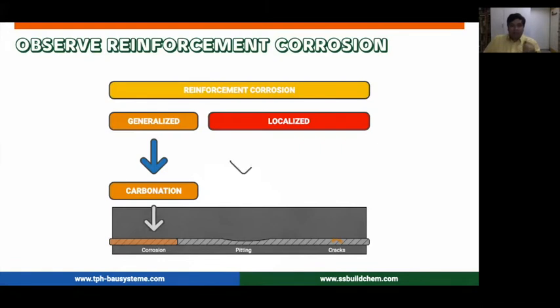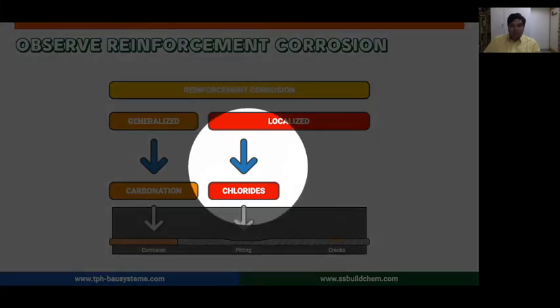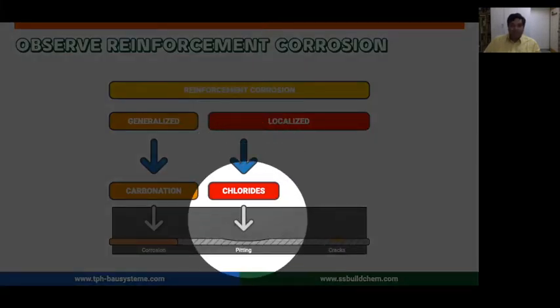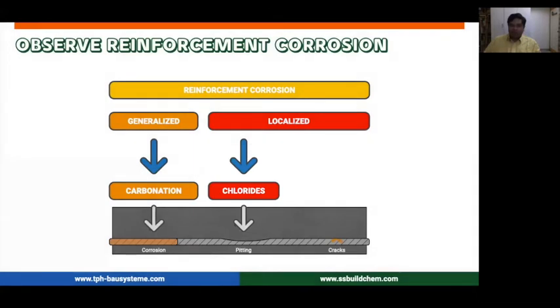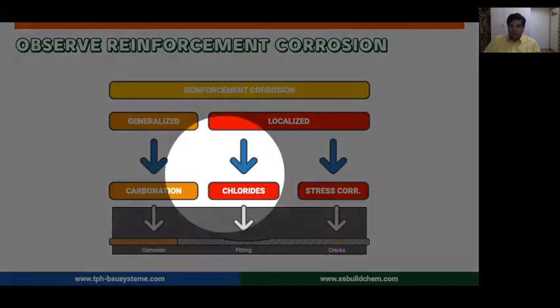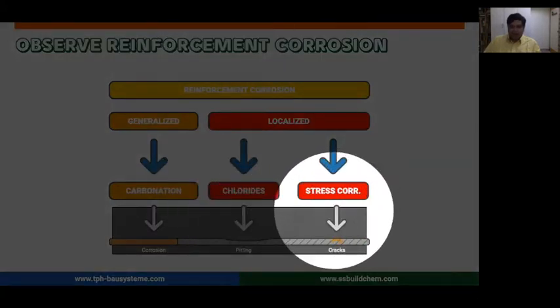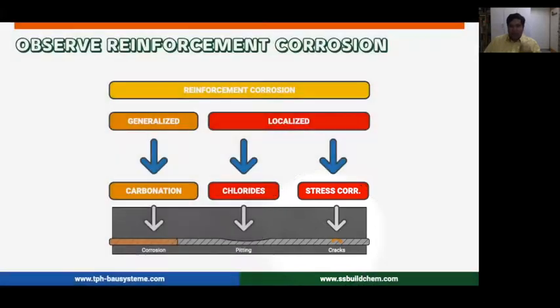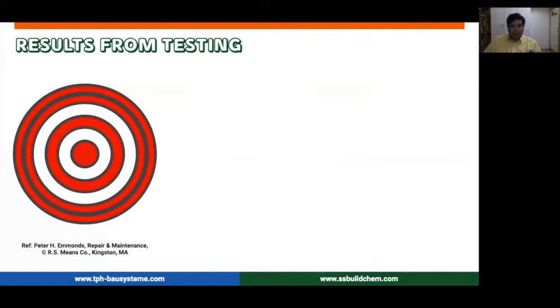Then, in case it is localized corrosion, it is much more dangerous, because one, it might be due to chlorides, and chlorides cause severe pitting, which means loss in the rebar section. It can sometimes also be due to a concrete structure being constantly under stress, under some creep. In that case, sometimes you also get stress corrosion in your steel, and you begin to see small cracks in your reinforcement. So a lot of times this kind of observation will also tell you a lot about what's actually happening to your structure.